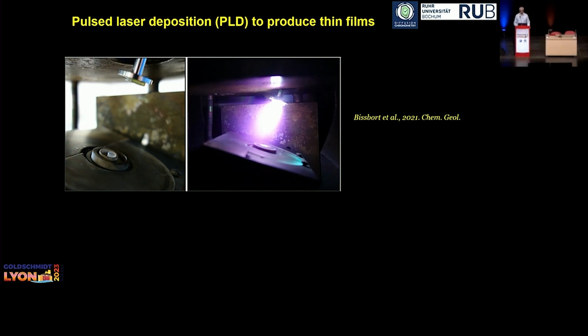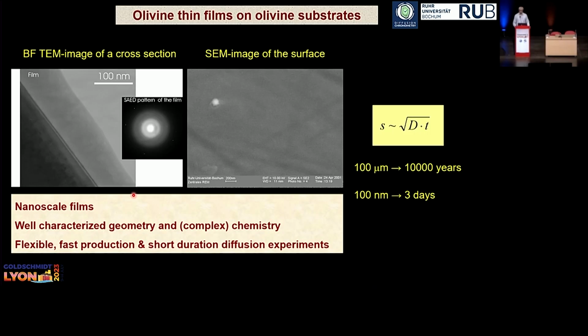What you do there is, those images are in a vacuum chamber, you're looking at a glass disk here at the bottom, which you call a substrate, another disk here on the top, which you call a target. And if you hit the target with a laser, you get a plasma, which then takes the material from the target and deposits it on the glass disk there. And what you produce, this particular image happens to be from a paper that Thilo Bissbort wrote out of his PhD thesis, but the instrument's been there for 20 years. And what you get are things like that.